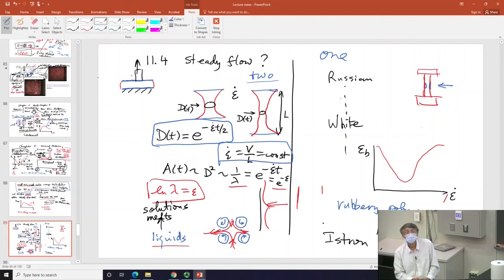So let me just give you a sense, then you will start to appreciate the difference. So suppose I can monitor this and make sure my diameter is shrinking exponentially like so. How do I make sure? I'll make sure my speed here is such that this is guaranteed. In other words, there is a feedback loop between them.